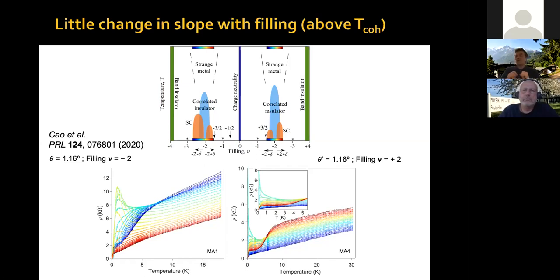Now, how do we measure the twist angle? There are several different ways of measuring, also depending on which type of experiment you're doing. So scanning nanoSQUID, scanning SET, the transport. You all can have different ways of measuring the twist angle. For the transport experiments, what we do is the following. We do 2 or 3 steps. The first one is to get a rough idea of what the twist angle is. For that, we look at the peak in resistance due to the insulator state, due to the band insulator.